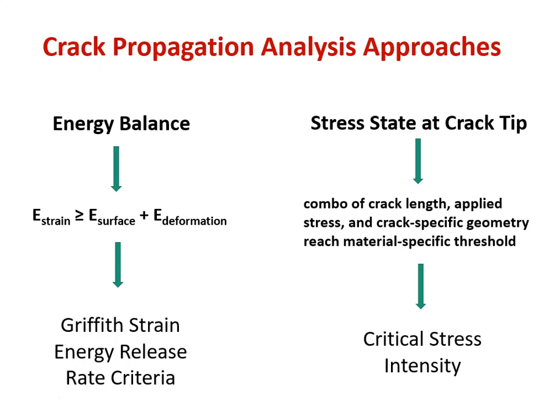We can also look at things from the standpoint of forces and stresses and strains, and that's really what we do with the stress state at the crack tip, where we try to look at the actual stresses right at the crack tip, and then relate that to the applied load, very similar to the way we looked at stress concentrators, except at really an atomistic level, right next to a very sharp microscopic crack in the microstructure. And so the important factors there are the crack length, which again is going to be on the same size probably as a grain length, but it could be bigger. We'll relate that in that case to the applied stress, and the crack specific geometry becomes important with that approach. And in that case, we'll come out with something called a critical stress intensity.